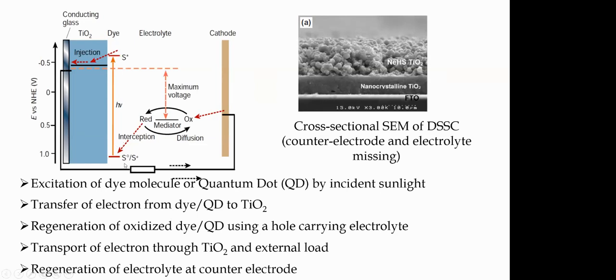This is a requirement that one has to make sure in selecting dyes: that the conduction band of the dye molecules should be above the conduction band of TiO2. Otherwise, efficient electron injection is not possible, and then the electron transport material will not work. So that is a design criterion that we need to take in these cases.